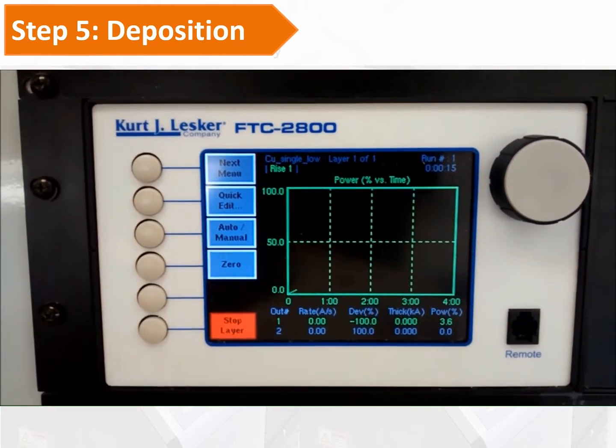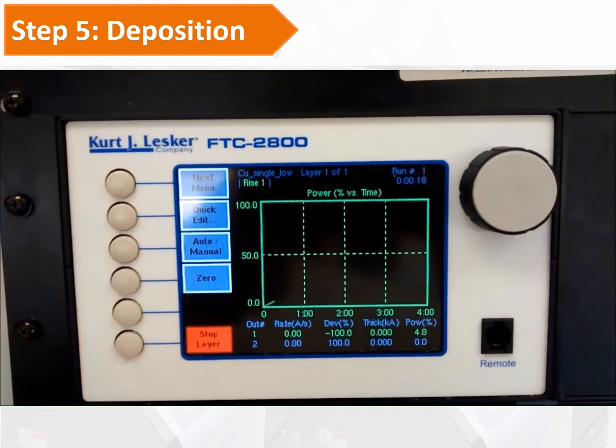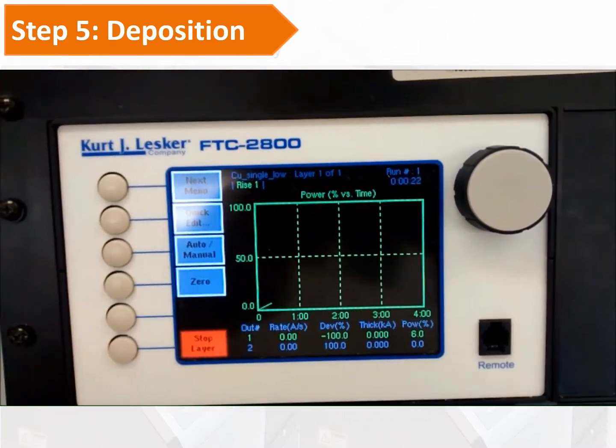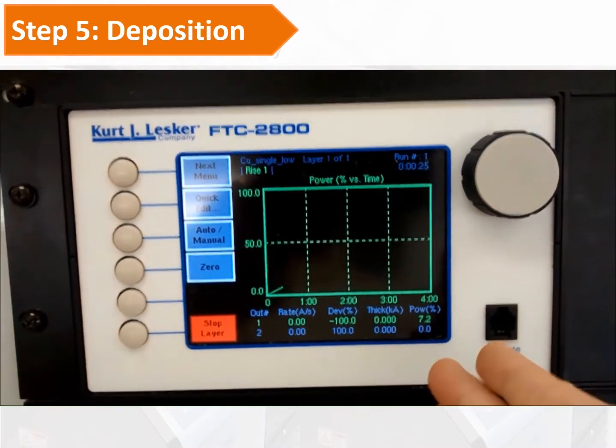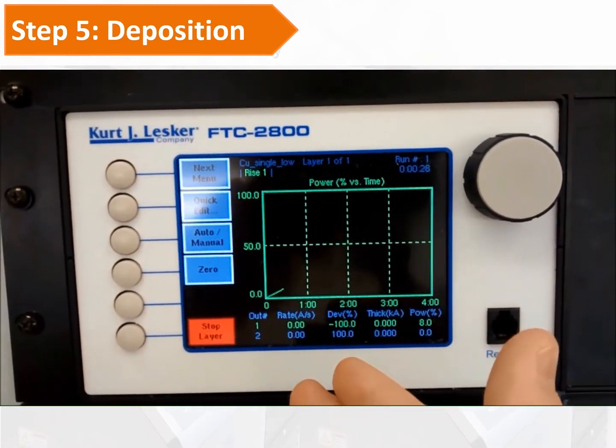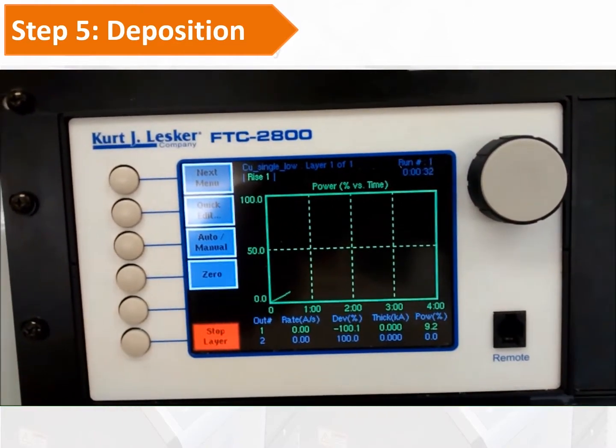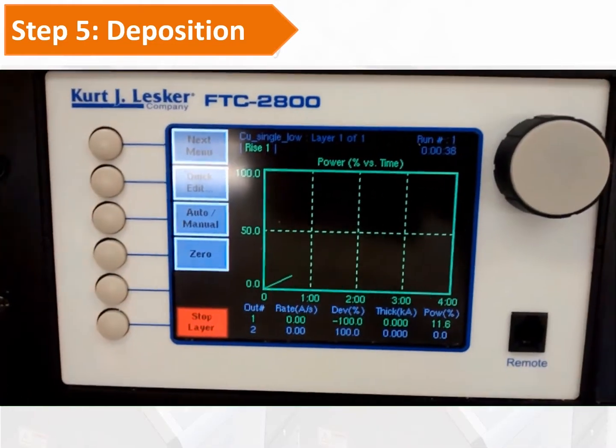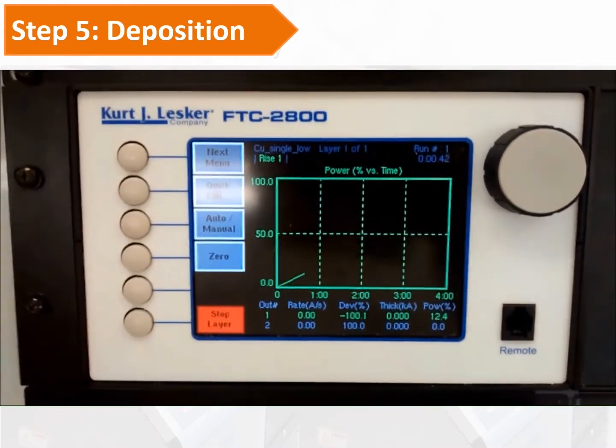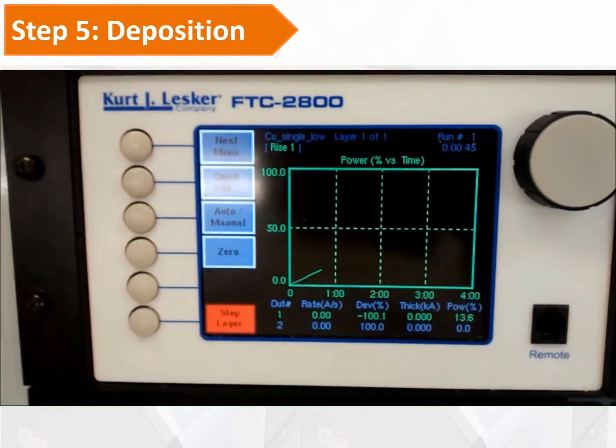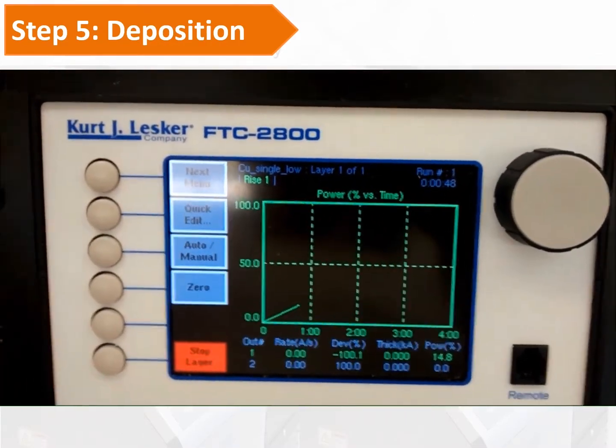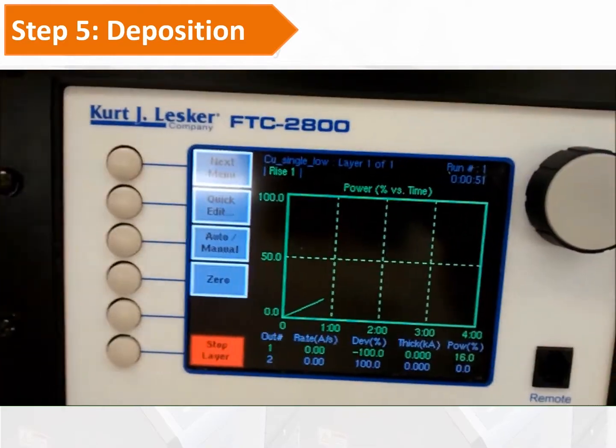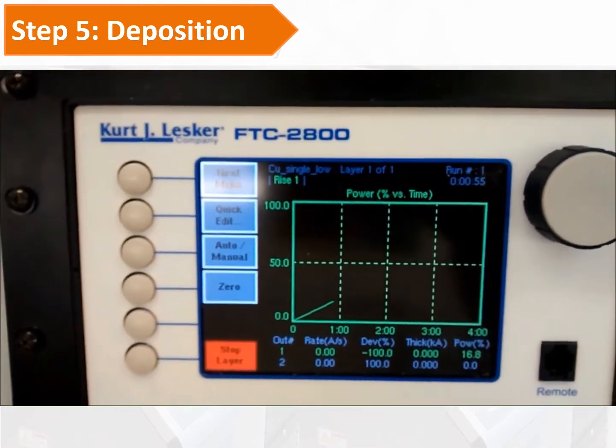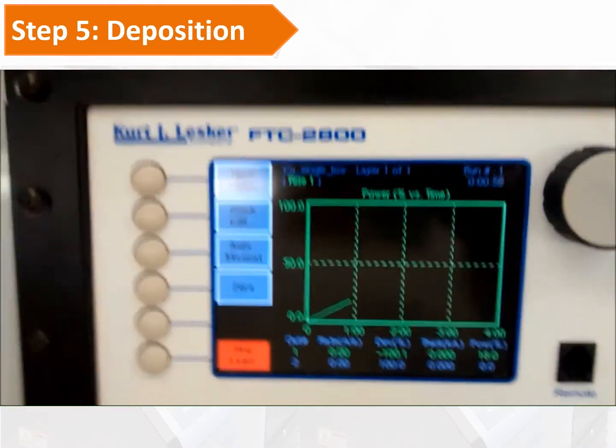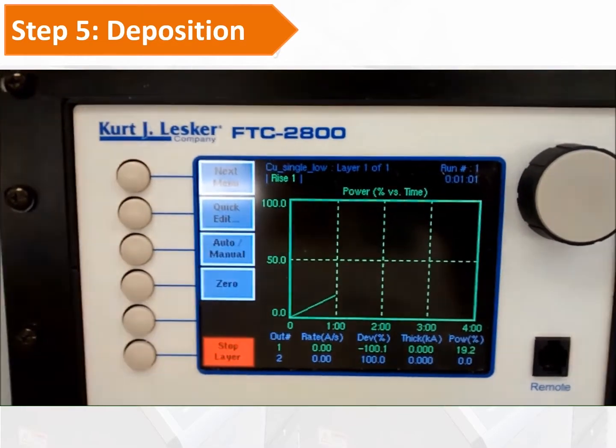Usually the evaporation process includes several stages: preconditioning, deposition, and post-conditioning. Preconditioning also has rise 1, soak 1, rise 2, and soak 2. In rise 1, the power will increase and we start to melt the material. Then we go to the soak 1 phase, where the material melts uniformly inside the whole boat. And we keep increasing the power again. We go to the rise 2 phase, and then the soak 2 phase, where we hold the power level. There is already some deposition rate, but it is low.